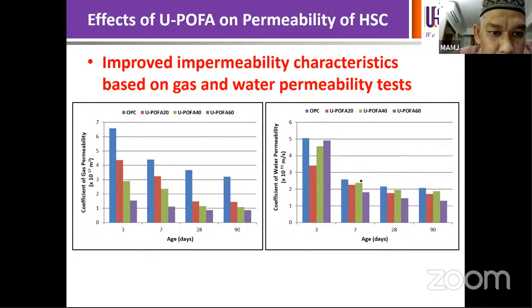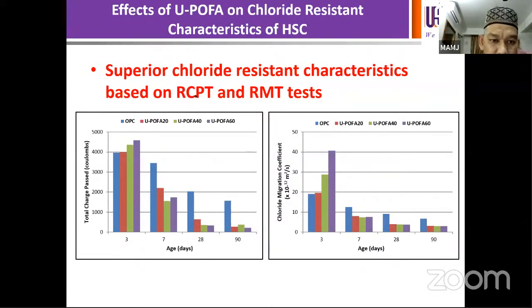All right, so in this particular case, it is showing coefficient of gas permeability as well as water permeability. So for both cases, we can see improved impermeability characteristics based on the two tests, gas and water permeability, which belong to the transport properties of the concrete. All right, and tests related to chloride resistance were also undertaken. So in terms of the RCPT, rapid chloride permeability test, we can see significant reduction in total charge passed, especially at the higher UPOFA content, right? And at a longer curing period of 90 days, for example.